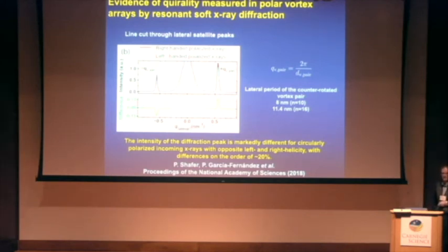Anything else? So I have a question. It seems that the nature of the domain walls matters a lot in terms of whether you can have an Ising-like, a Néel-like or a Bloch-like wall, and the mixture of those to get a vortex state. So is this general for a tetragonal ferroelectric, or can this live in a rhombohedral or orthorhombic ferroelectric, where you might have more possible domain states to relax into?